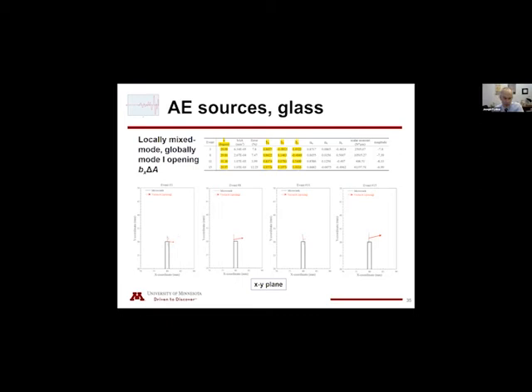So this is a representation of the plane itself, not the normal. So this is the little crack, and this is the opening that has taken place with some tangential component in this plane. This is event 8, again mainly opening, but there is some Y displacement. Event 11, and the arrow does indicate the magnitude. We're just writing this in terms of B, but there is a delta A there, so we can't take out the delta A. B delta A is a measure of the magnitude. We can compute what's called a scalar moment, and then also compute the moment magnitude. And then this last event.